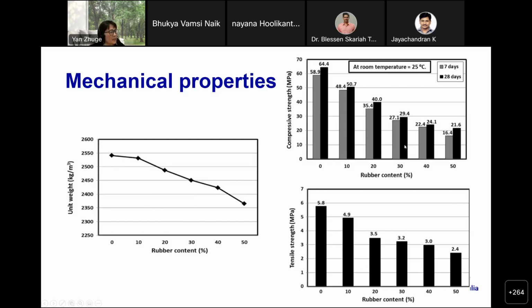And this is the compressive strength. You can see when you use 30% or even more, there is a sharp drop of the 28-day compressive strength. It could drop from about 65 megapascals to about 20 or 30 megapascals. So that is an issue for the compressive strength.